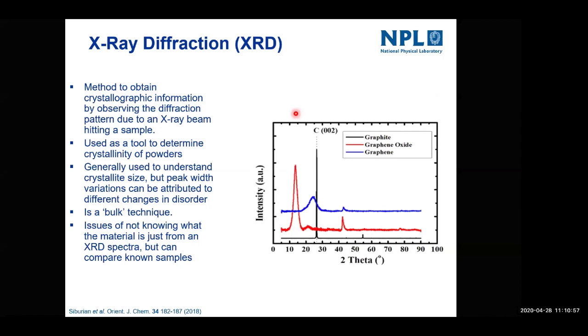If you look at the academic literature, you'll see instances where just one measurand of some description has been controllably changed, and therefore you see a change in, say, peak position or peak width. It doesn't mean that you can take a material and then put another material in, and we see the same issues with Raman, and go, okay, I determine that this is a quantified quantity with an uncertainty for this measurand, because obviously that was a controlled experiment, but it does show differences. So again, it's not necessarily as quick as, say, doing an optical technique, but typically it will be on the order of, say, maybe hours rather than days of measurement of many flakes. So yes, a powerful technique in that respect.